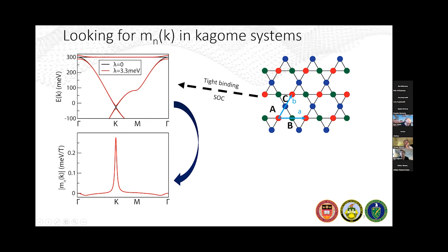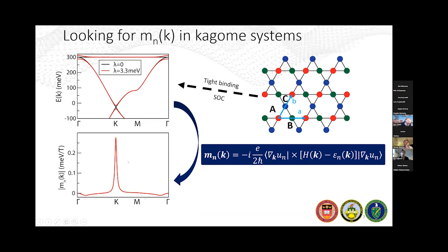So once you introduce a little bit of spin-orbit coupling, some of these crossings actually split. Here, the Dirac point is going to result in a Dirac gap, and you also have lifting of the degeneracy here. So if you calculate for this kind of electronic band structure the orbital magnetic moment, let's say for this Dirac band here, the upper part of the Dirac dispersion, you will see substantial orbital magnetic moments concentrated at K. This comes from the non-zero Berry curvature concentrated primarily at the bottom of this Dirac dispersion.